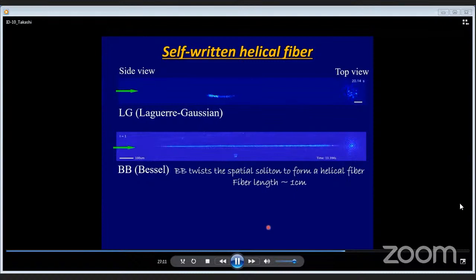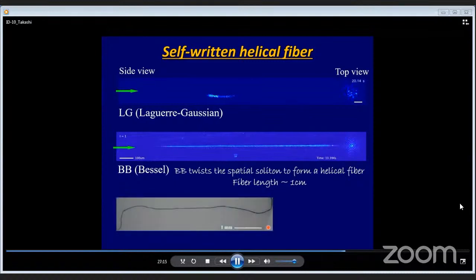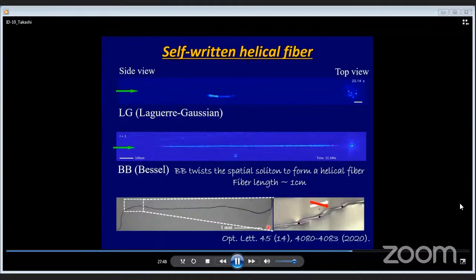I would like to show you an optical microscope image of the fabricated fiber like that. Beautiful fiber is created. Typical diameter of the fiber is about 3 microns. Length of the fiber is over 1 centimeter, typically 1 centimeter. Maximum value is 1.5 centimeter. That corresponds to the thickness of the cell, you know. Quite long scale fiber can be fabricated. This is a magnified image of part of the fiber. You can find this fiber is twisted well. Such helical fiber creation must be a breakthrough for the microfabrication technique, definitely.